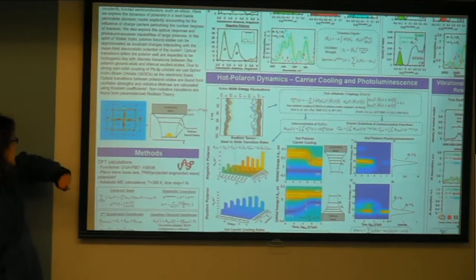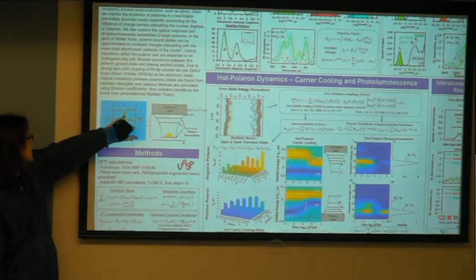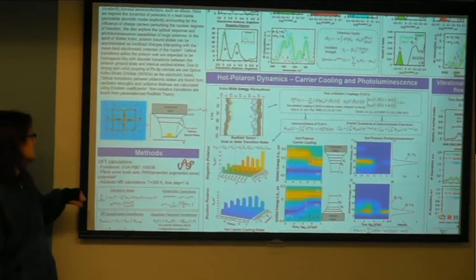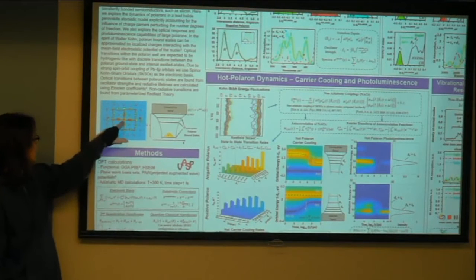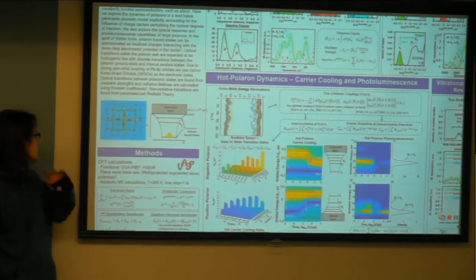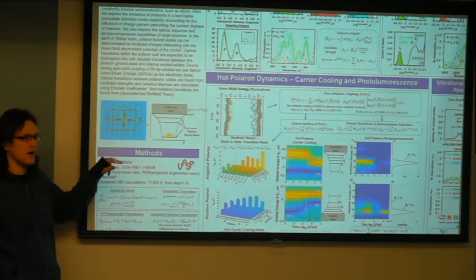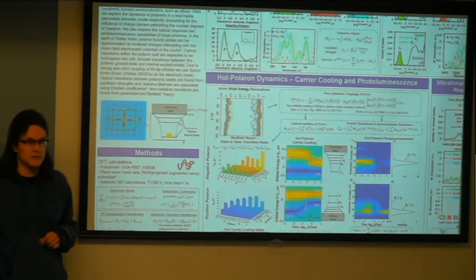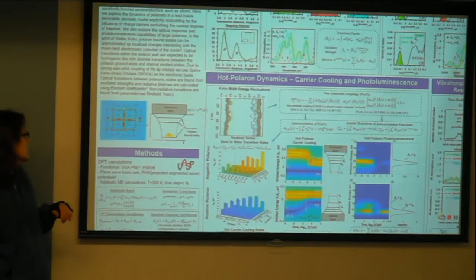Those are the sticks and balls, and these different colors represent charge. So you put a charge into the box, and due to these materials being soft, there's a lot of nuclear reorganization. Due to the change in the coordinates of the ions, the charge becomes self-trapped, known as a polaron.